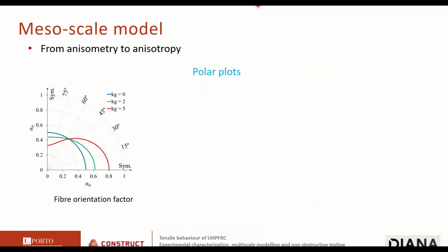So, how do we use this? So we must go from an anisometry, so the description of the different fiber orientations with the different directions. We must go to the mechanical properties of the material. Using these models, it's possible. So here you have different distributions of the fiber orientation factor. So this is a polar plot. Okay. The red line corresponds to a probability density function with very well oriented fibers. The blue curve is a probability density function with no preferential fiber orientation, in which the fiber orientation factor is constant no matter the direction.